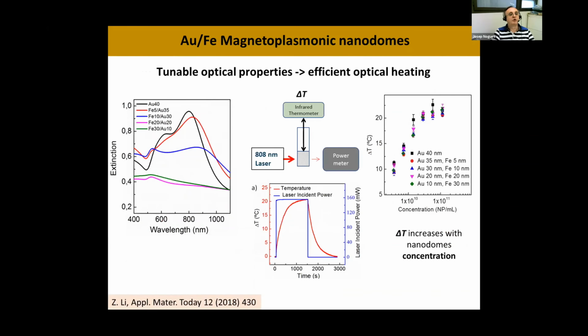As for the optical properties, we can see here that pure gold has a nice plasmonic resonance at about 800 nanometers. Importantly, this wavelength is in the first biological window, where the light penetrates the most inside the body. Also, as we start adding iron into the system, first there is a redshift of the plasmonic resonance, and there is also a damping of the plasmonic resonance. As I said, this can be used for heating.